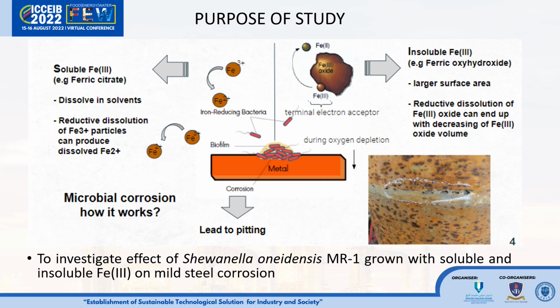So MIC works when the metal samples incubated with Shewanella get corroded via reductive dissolution of iron 3 particles to dissolved iron 2, using either ferric citrate or HFO as terminal electron acceptors. These iron 3 reduction mechanisms of Shewanella oneidensis MR-1 will remove the protective layer of iron 3 formed on metal samples, eventually leading to pitting corrosion within the incubation period.